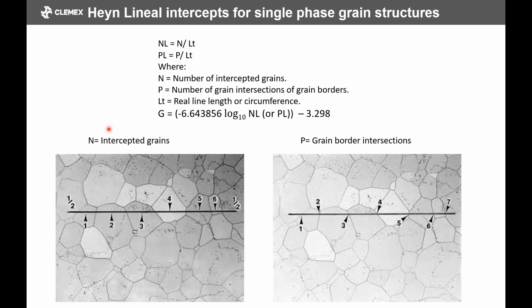The lineal intercept method for single phase grain structure. It's important to mention single phase grains because normally if you make a straight line, you need to make sure that you have a single phase, so you don't end up with 2 or 3 different phases, which would need various orientations of the line to make sure that you have something more random.